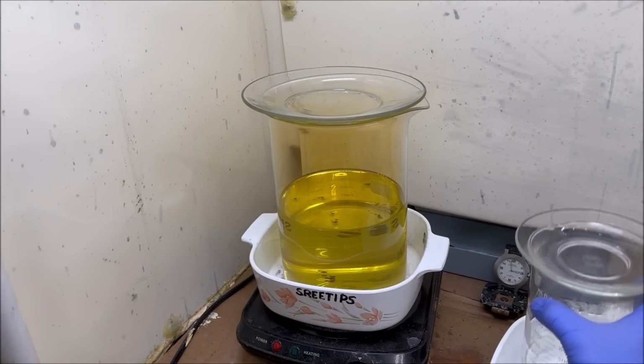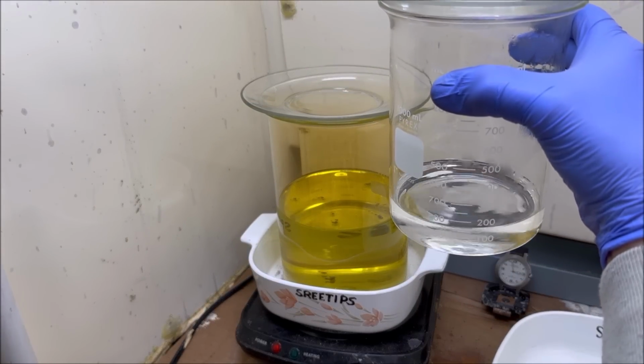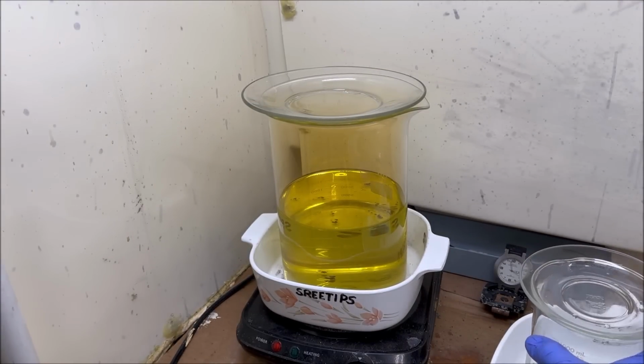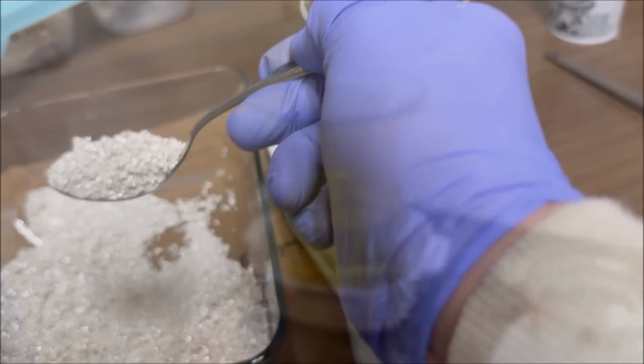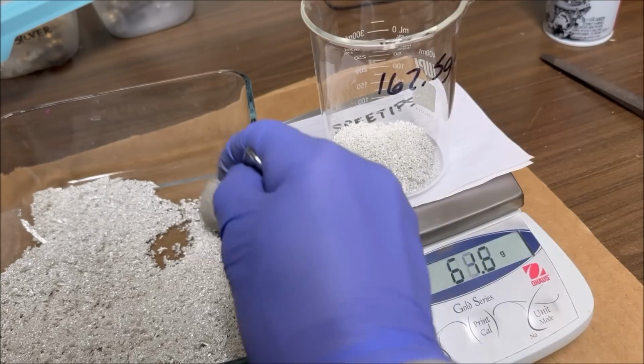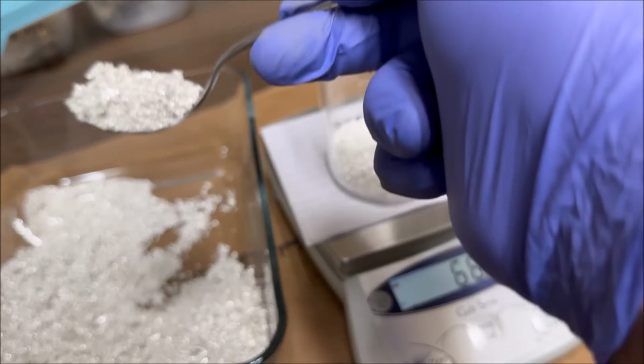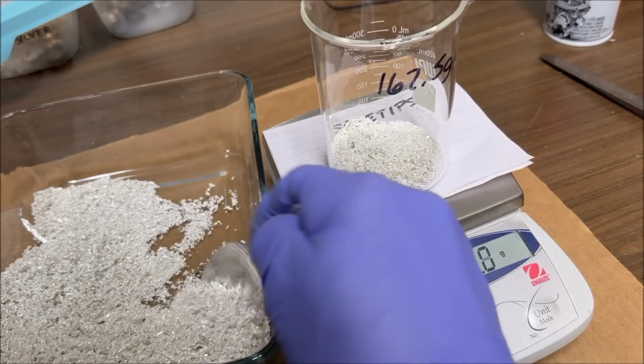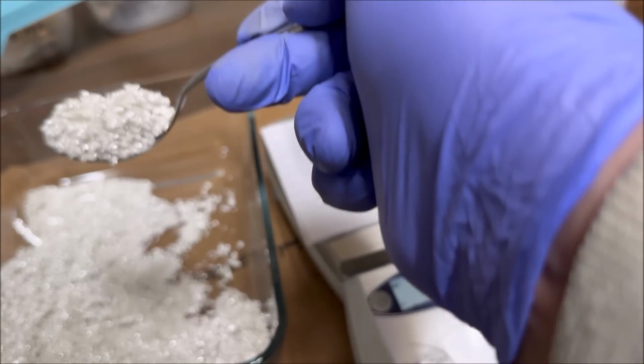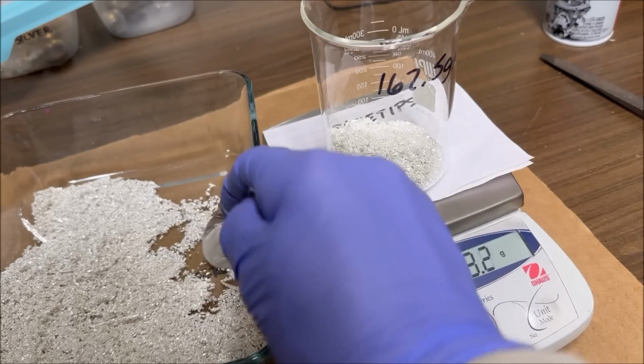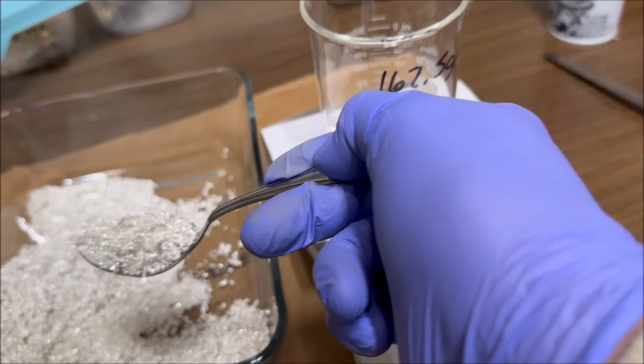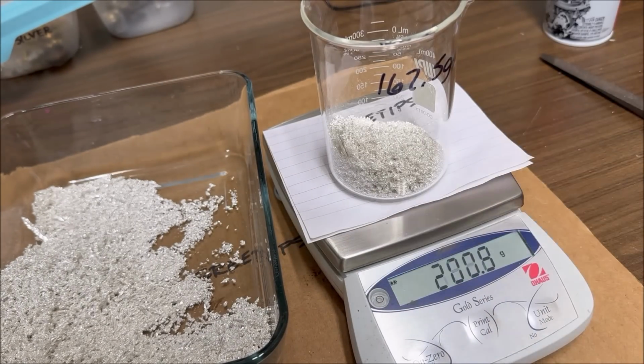Here you can see all the silver bars have been dissolved. It only took 900 milliliters of nitric acid. You can see there's still excess nitric in that solution. So what I'm doing here is measuring out some of the pure silver crystal from my electrolytic silver cell, and we're going to use that to consume the rest of the excess nitric that's in the electrolyte.